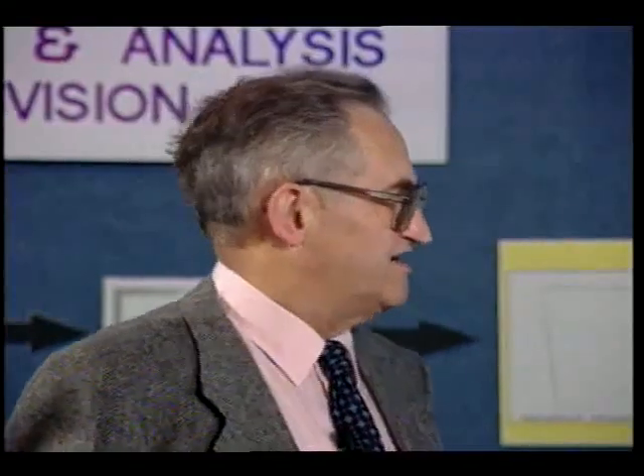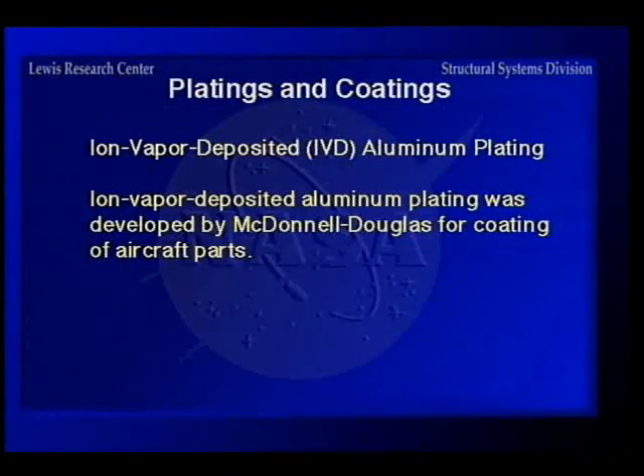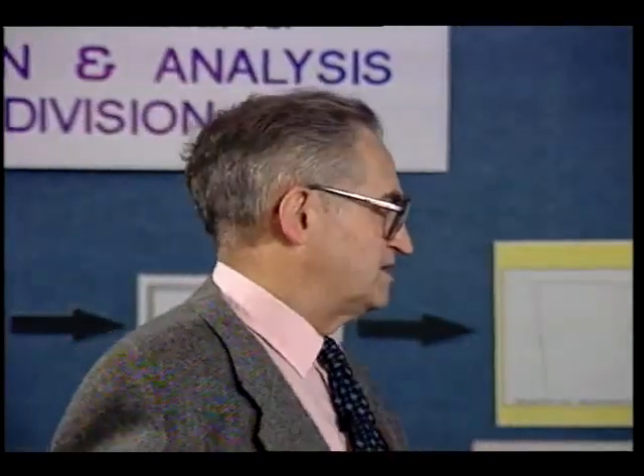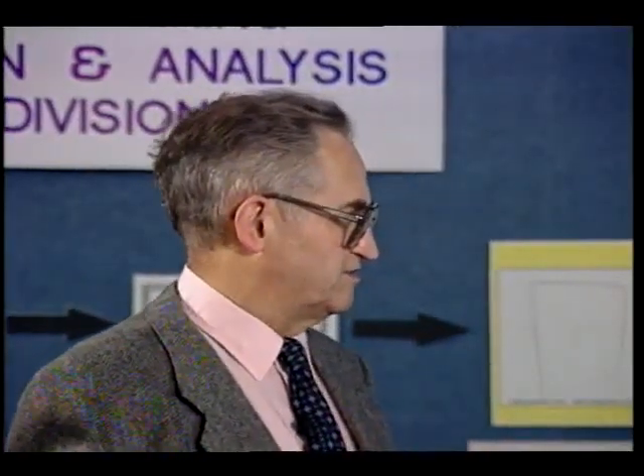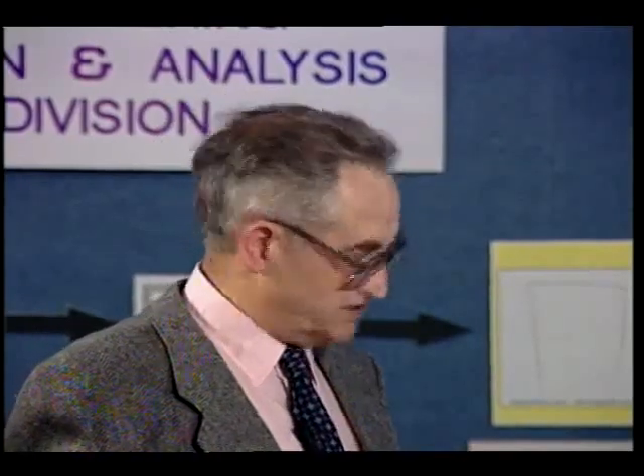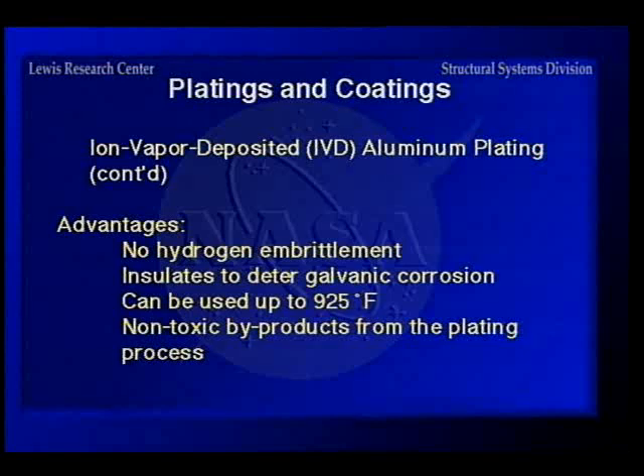Now here's the ion vapor deposited aluminum plating. This is a special one that was developed, I believe, by McDonnell Douglas for coating of aircraft parts. And it was going to be used as an alternate to cadmium plating. Well, it doesn't give you hydrogen embrittlement, and it insulates to deter galvanic corrosion, and can be used up to 925 degrees, and doesn't give off any toxic byproducts.